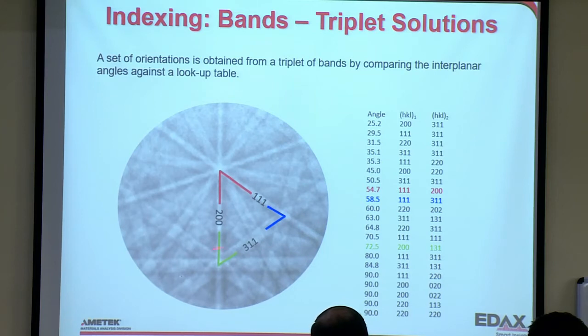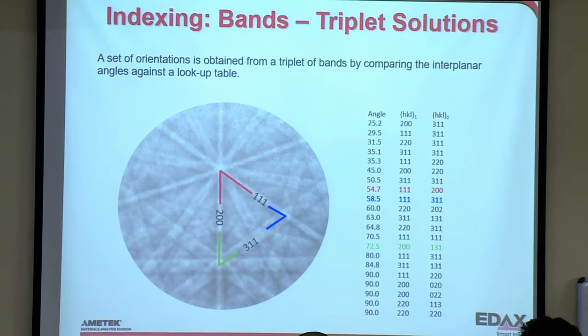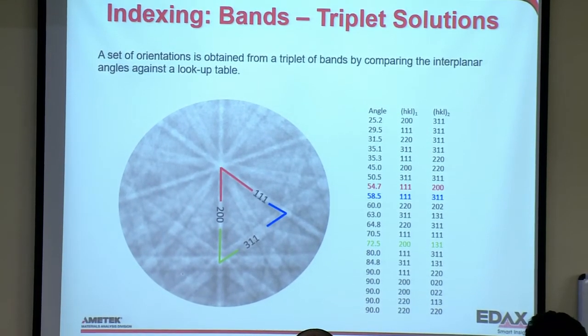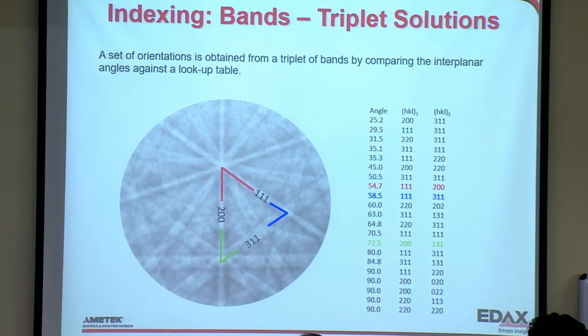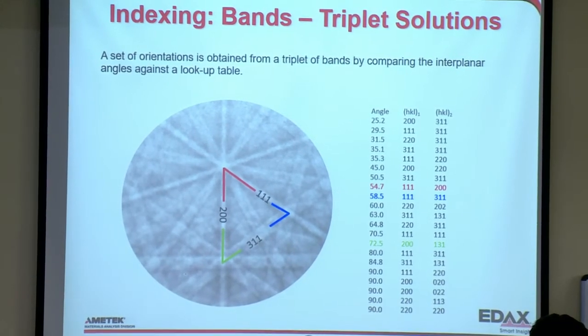And we do the same thing down here for this one, and then we know the orientation. So with 3 bands, we do know the orientation. With 2, you could do it with 2 if you could really identify the widths. But the Hough transform is not very good at finding the widths of the bands. So we use 3 and just use the angles, because the Hough transform is good with angles. We can get angles within probably 2 to 3 degrees.